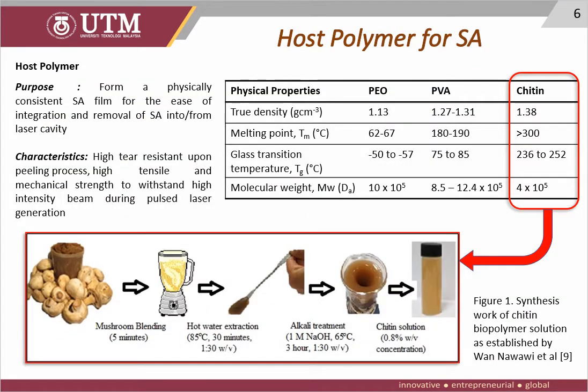A host polymer is needed to form a physically consistent SA film for ease of integration and removal of SA into the laser cavity. And in this research, we introduced natural biopolymer as a non-toxic alternative to conventional polymers such as polyvinyl alcohol, PVA, polyethylene oxide, PEO, and many other conventional polymers. So chitin shows comparable properties to the other polymers and is proven to have the characteristics to become the host polymer for SA, which are high tear resistance upon peeling process, high tensile and mechanical strength, and withstanding high intensity beam during pulse laser generation.